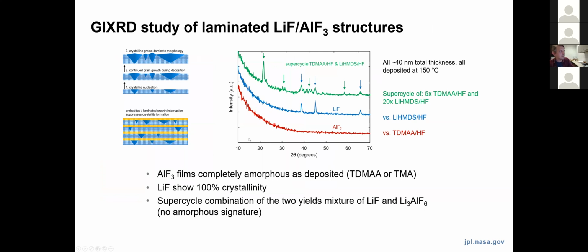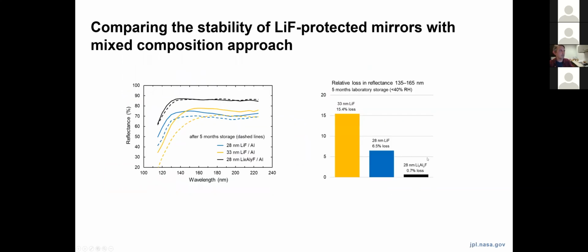One example of that type of engineering is creating mixture materials. Since we're depositing these materials one atomic layer at a time, we can mix the atomic ratios at arbitrary compositions. And so that's one thing we've been looking at in mixing lithium fluoride with aluminum fluoride to improve the stability versus